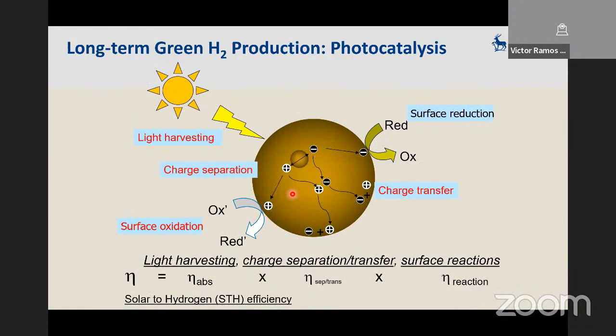Now, the long-term holy grail for hydrogen production from solar, as I mentioned, is photocatalysis. Photocatalysis, for those familiar with catalysis, is a surface phenomenon, and the chemical reaction is happening on the surface of a nanoparticle, in this case a semiconductor nanoparticle, like titanium dioxide nanoparticle, or any other semiconductors. When you have photons irradiating the surface, the electrons and the holes will separate. The electron and hole will recombine in the bulk and also on the surface. And the trick is to really enhance the light harvesting, which has to do with the electronic structure of the semiconductor, and the charge separation and transfer process efficiency, and the surface reaction.